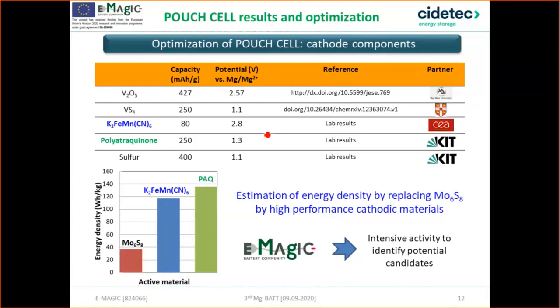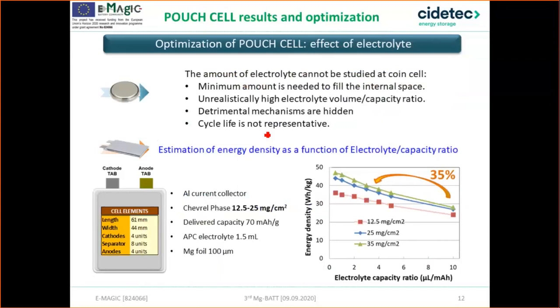Back to Chevrel phase and analyzing the effect of other components, like the electrolyte. Coin cell is not a good system for studying the amount of electrolyte because there is a minimum amount of electrolyte to fill the internal space. Consequently, the volume capacity ratio is not realistic in a real prototype. This high amount of electrolyte hides the detrimental mechanism in the cell, and consequently, we have overrated cycle life. That's why the effect of the electrolyte must be studied at pouch cell level.